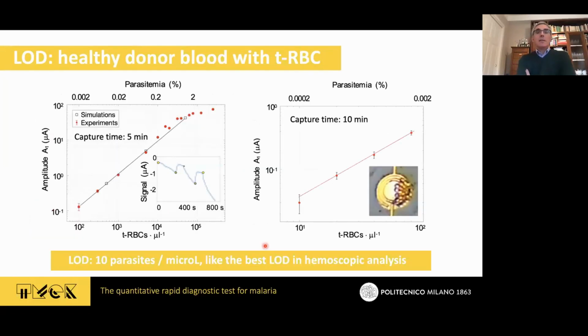How much is it quantitative? It can be seen from these experiments. This is an experiment carried out using a blood sample from a healthy patient. So we took out some red blood cells. We treated them in order to obtain some red blood cells with methemoglobin, mimicking now infected red blood cells. And we measure now the signal amplitude as a function of the concentration of treated red blood cells. And as you can see, we found a signal trend which is almost linear from 100 treated red blood cells per microliter up to 10^5, which means that we have at least 3 decades in which we can use quantitatively our test, because you see there is a linear correlation here.